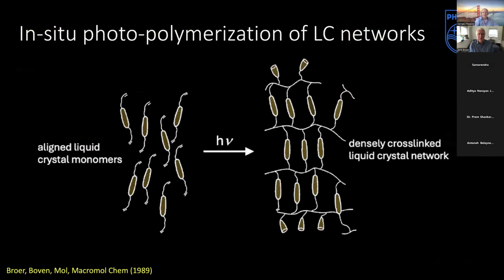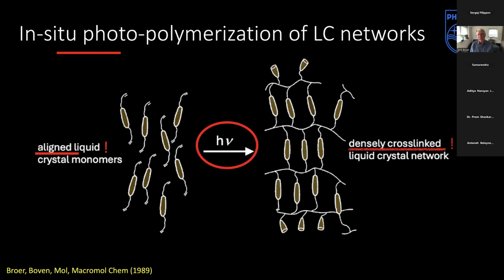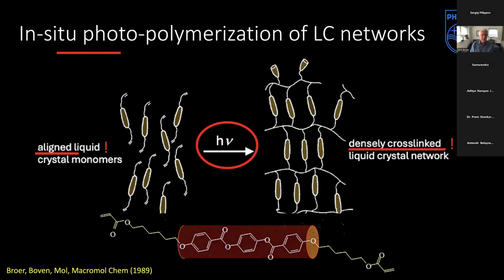I came into the field in the second half of the 80s of last century, and I developed, while working at Philips, the process of in situ photopolymerization of liquid crystal networks. The difference with the state of the art at that moment was that I started with aligned liquid crystal monomers. We modified the liquid crystal such that it could be polymerized by reactive end groups. It could be aligned just like normal low molecular weight liquid crystals, and then by UV light you could photopolymerize the material to form a densely cross-linked network.